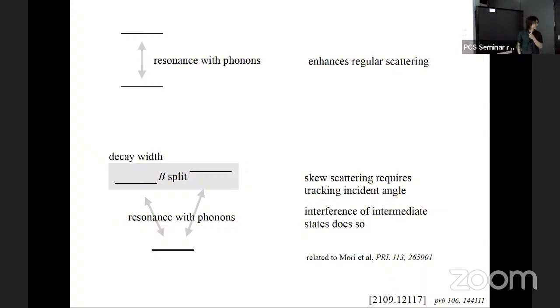large Berry curvature phonon. That's a very important point. Because in the previous STO example, the Berry curvature is large only because the dielectric constant is large. But now in general materials, there's no large Berry curvature. So we should not rely on large Berry curvature. We should rely on this mechanism.